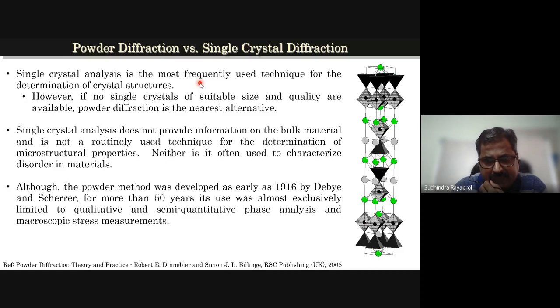You have to have high quality. In case of X-rays, it has to be good enough that it doesn't absorb, but it should be big enough to scatter properly. In case of neutrons, it is worse because you need a bigger crystal because of the weak interaction with neutrons, and it has to have very good scattering also. So single crystal is very, very demanding.